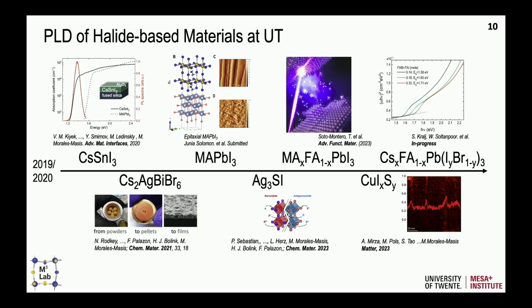This is a picture of the film, and this is how it will look in the same image. And by using this principle, the idea is if we want to go volatility independent, then we can work with many different materials, from very standard cases, for example, cesium tin iodide, methylammonium lead iodide, and these combined cations like methylammonium formamidinium. But also because we are so independent of these materials, we can actually go for even material discovery, which means we go for things that are even more complex, like, for example, the case of chalco halides, perovskites that are also very interesting nowadays.